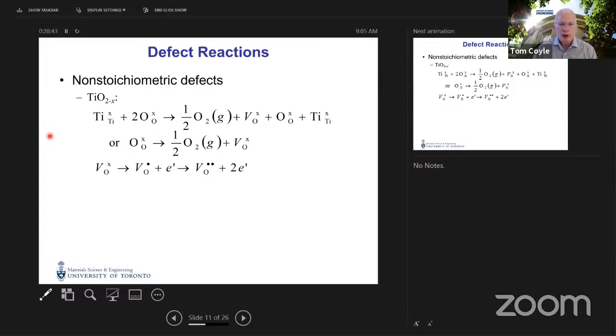Now that may not be the end of things. That vacant oxygen site may release its electron into the conduction band. And it may release one electron, as shown in the first part of this reaction, where that vacant oxygen site with its 2 electrons gives up an electron to the conduction band, leaving behind still a vacancy on the oxygen site with only 1 electron localized to that site in the lattice.